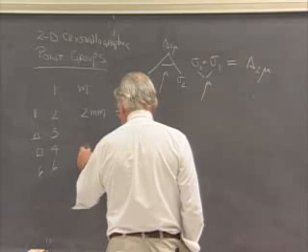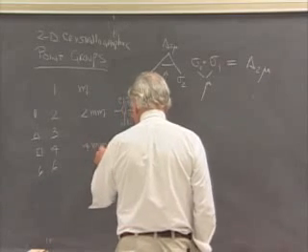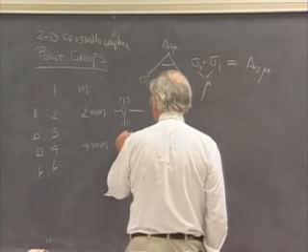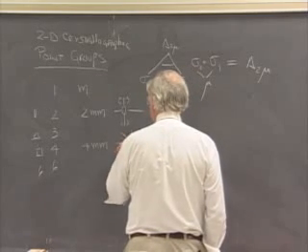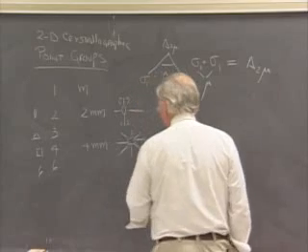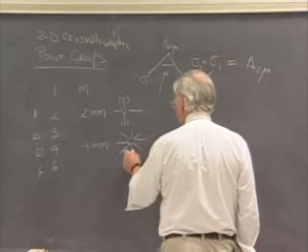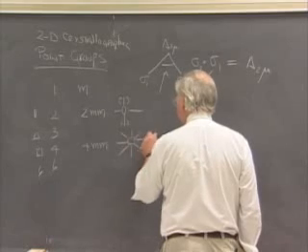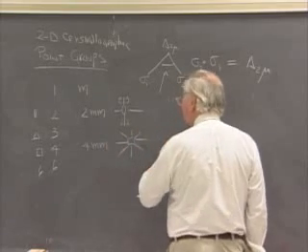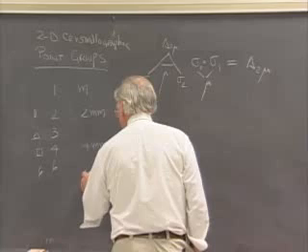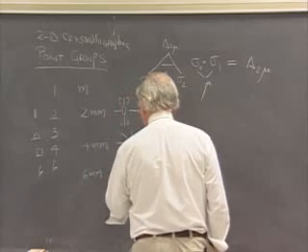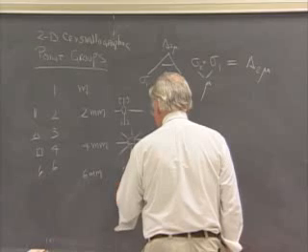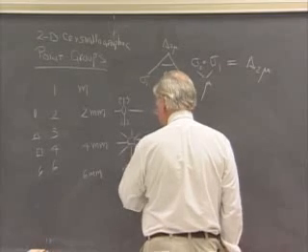For a four-fold axis, we could add mirror planes, and they would have to be at half the angle of the four-fold axis. And as we saw, it was kind of a mouthful to call this 4mm. There were just two kinds of mirror planes, so this one was called 4mm. 6mm analogously was a six-fold axis with mirror planes separated by 30 degrees, half the throw of the six-fold axis.